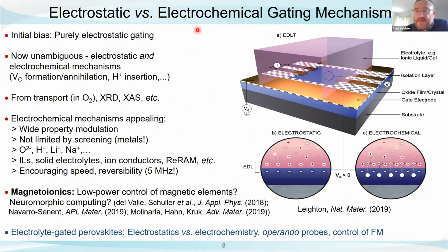Is the mechanism electrostatic or electrochemical? So the initial bias, if you'll pardon the pun, was that it would look something like this, simple electric double layer charging, like I just talked about. But we now know from a lot of experiments on a lot of systems, including oxides, that electrochemistry often occurs. In an oxide material, for instance, the electric field at that interface is so big that it can remove negatively charged oxide ions, forming oxygen vacancies, doping the material that way. And then when the electric field is reversed, these oxygen ions can be driven back in. They can annihilate the oxygen vacancies, and we get a reversible cycling mechanism that has very little to do with simple electrostatic charging, okay?